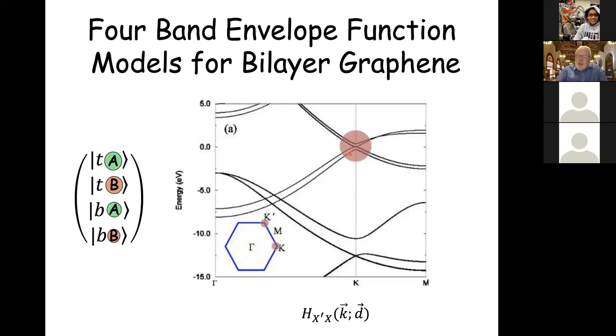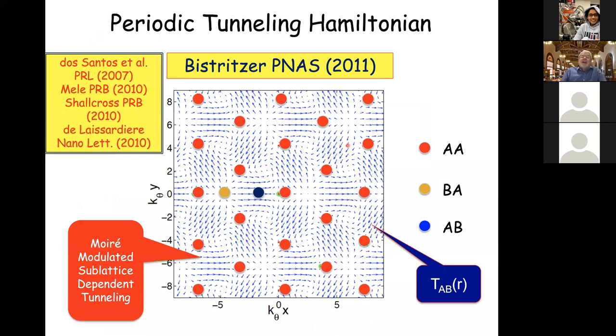When you have a twist between the layers, that interaction between the two layers will be present, but it will be position dependent because it's dependent on the coordination between the two layers. And now I'm showing you a figure from a paper that I wrote together with a postdoc, Rafi Bistritzer, about a decade ago, in which we tried to make some points concerning the electronic structure of twisted bilayer graphene. And this illustration is showing the hopping between one layer and the other as a function of coordination.